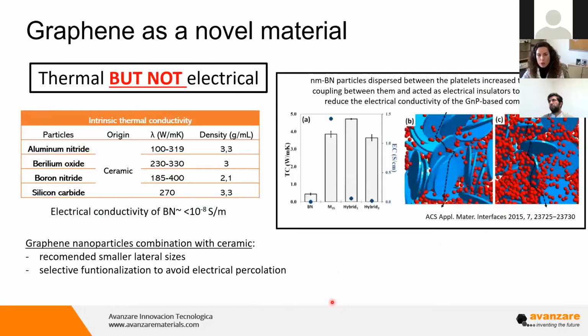What happens when we want to have thermally conductive composites but electrical insulators? In this case, what we are doing is mixing our graphene nanomaterials with ceramic ones. As you've seen before, ceramic ones also have high thermal conductivity and at the same time are electrical insulators. For example, boron nitride is about 10 to the minus 8 Siemens per meter. So what we can do is allow phonons to move, but put these ceramic nanoparticles in the middle to prevent electrons from moving and producing high electrical conductivity.